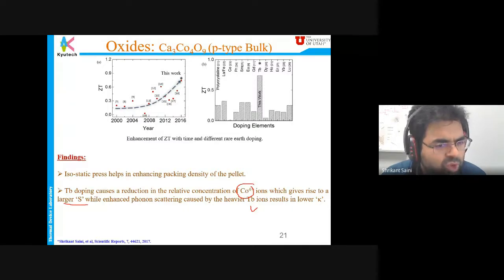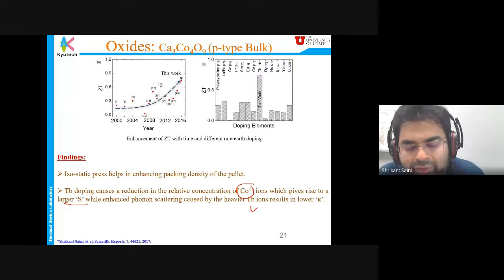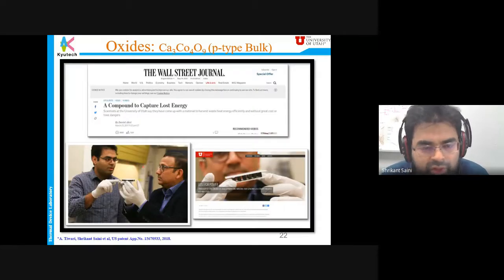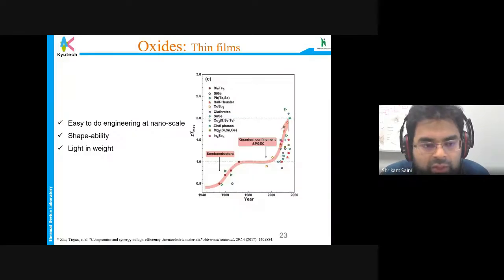People have been working on this material since 2000, and in 2016 we reported this as the best thermoelectric with terbium doping. When we reported this, it was covered in many different international media, one of the best I believe being the Wall Street Journal. This work also led to a patent in our case. This material has been commercialized already. And this is the one thing about the material.